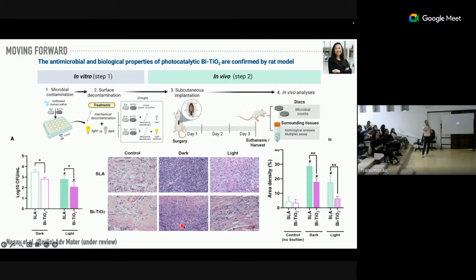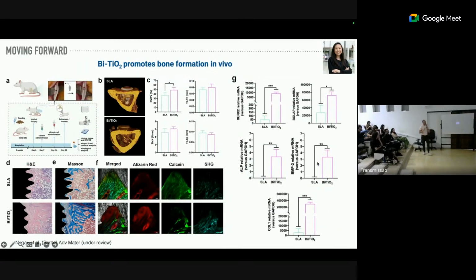We also observed a reduction in terms of inflammatory cells, as you can see here in this graph. We also checked the bone formation using in vivo analysis. As you can see, we use the tibia of these rats with the surface treated with bismuth and SLA. SLA we use because SLA is a very common surface treatment for dental implants. As you might see, in terms of micro CT, there's not much difference across the groups, which might be very good because we are not looking for something that is better than SLA.